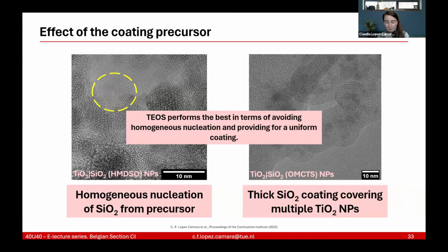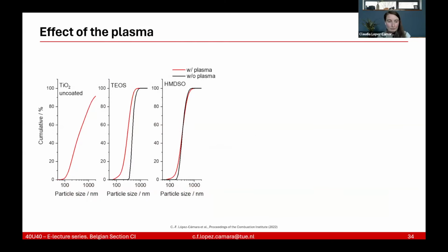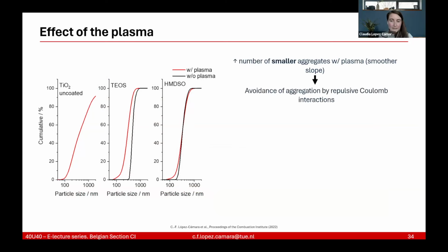So with that knowledge, we were like, okay, well, what about the plasma? Does it help or not? And we saw, based on this analysis, that there was a higher number of smaller aggregates when plasma was present, which means that there is a smoother slope. That's clearly seen in the case of TEOS. And that means that there is avoidance of aggregation by repulsive Coulomb interactions, which basically translates to the fact that, okay, plasma works.